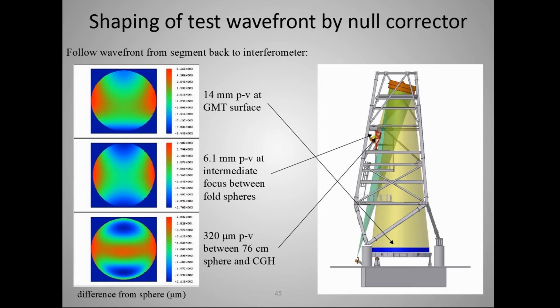That's what the figure looks like of the mirror. 14 millimeters of departure. After the first bounce off the first fold sphere, it's reduced to 6.1 millimeters. And after bouncing off the second fold sphere, 320 microns, which is fixed by the holographic optical element before going into the interferometer. And of course, from the interferometer, it goes through the fold spheres and holographic optical element twice, one bounce off of the primary. So I forgot, someone said that there's like 19 surfaces that we have to worry about the alignment of, non-trivial.